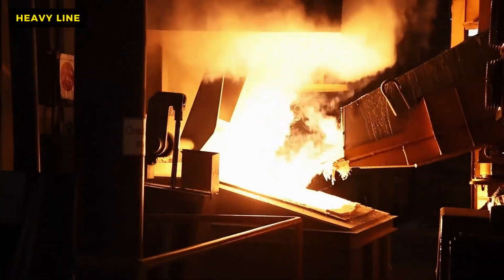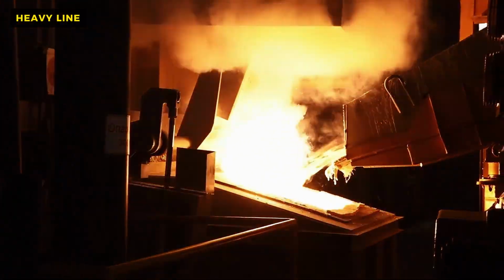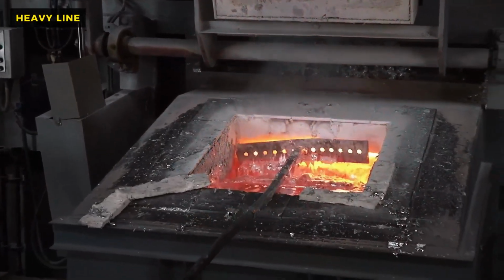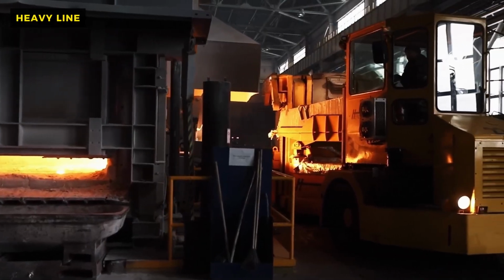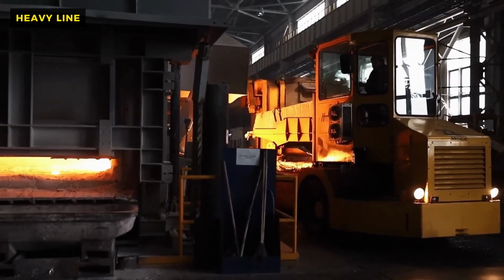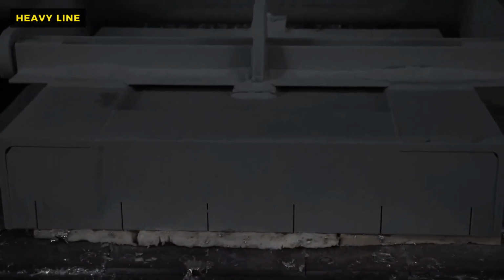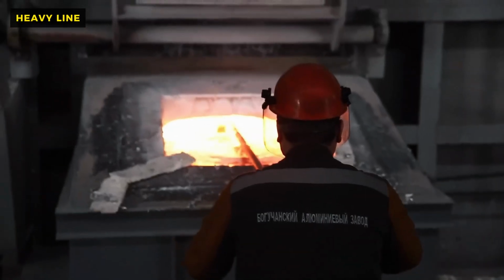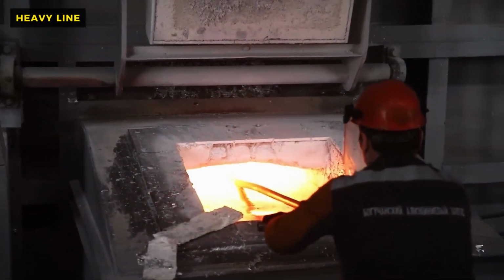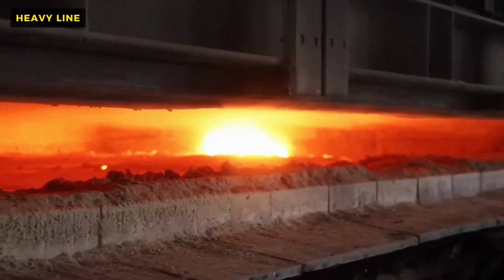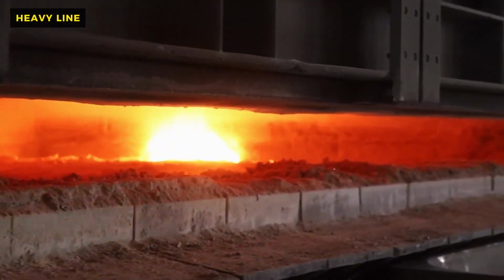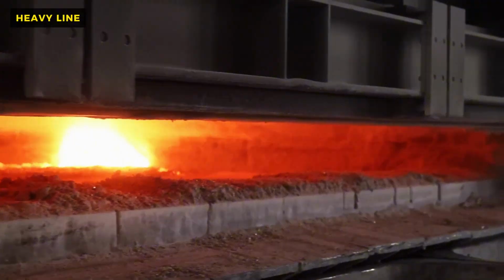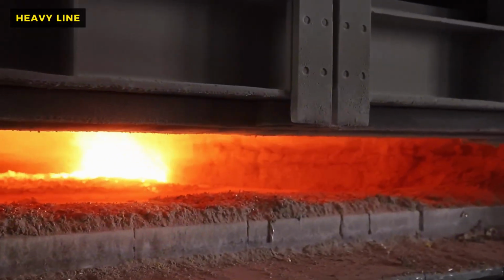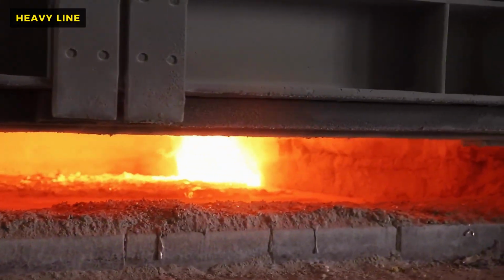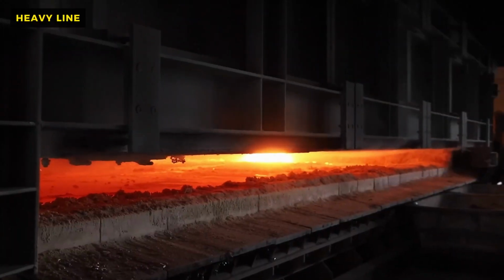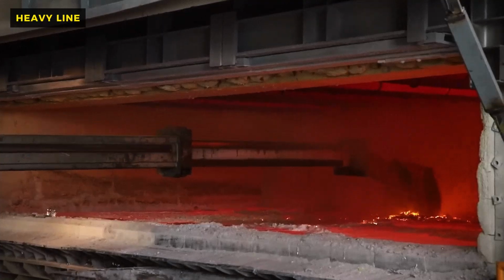Transition your focus to the reline shop, the place where old pots go to be reborn. A reduction cell has a lifespan of about 5 to 7 years before the carbon lining fails or the steel shell deforms. When a pot is taken out of service, it is allowed to cool, a process that takes days before being demolished. The spent pot lining, infiltrated with fluorides and cyanides, is a hazardous waste that requires careful handling and treatment.